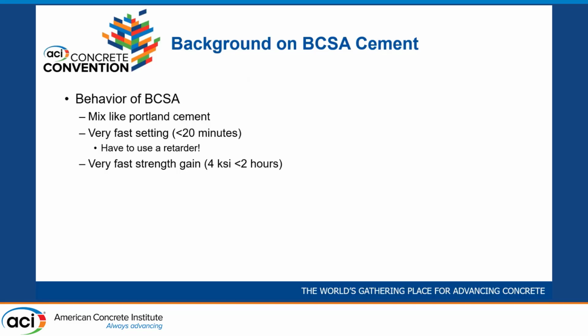A benefit of BCSA compared to some of the other alternative cements is that it can be mixed very similarly to Portland cement. So you just add water and mix it up. It tends to have a very fast setting time, less than 20 minutes. So basically you have to use a retarder in order to use it for most applications. It also has very fast strength gain. We can usually achieve 4,000 PSI in less than two hours pretty easily.